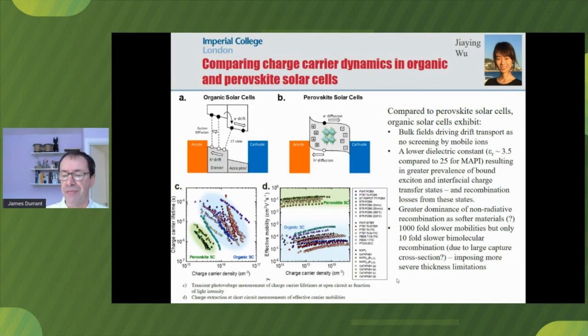That has many implications. It means you get far more bound states — excitons or interfacial charge transfer states — in the organic solar cells. Recombination losses from these excitons and CT states are one of the limiting factors in organic solar cells. Organic materials are typically softer materials and exhibit greater non-radiative losses. Carrier dynamics in organics are far slower than in MAPbI3 and other perovskite materials. Carrier mobilities may be a factor of a thousand times faster in a perovskite than in most organic materials. Recombination dynamics are unfortunately not a thousand times slower in organic materials — typically it's only around ten times slower in an organic bulk heterojunction blend compared to a perovskite. That difference is probably associated with the difference in capture cross-section because of the difference in dielectric constant of organic materials versus MAPbI3.